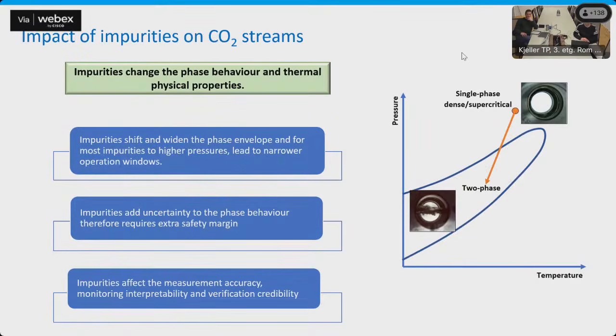So the most important impact of impurity is that impurity changes the phase behavior and the thermophysical properties like density, viscosity, compressibility, and speed of sound, for example. Impurity shifts the phase boundary, widens the phase envelope, for most impurities to higher pressure. This leads to narrower operation windows. Impurity also adds uncertainty to phase behavior. This requires us to set an extra safety margin to account for the impact of those impurities. Impurity also affects the measurement accuracy, monitoring interpretability, and verification credibility.